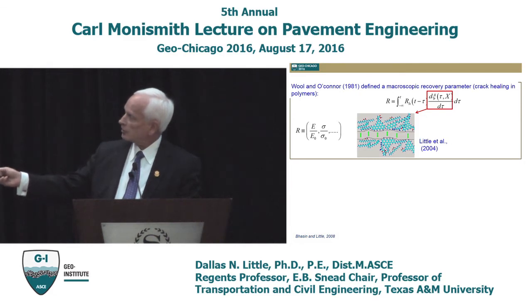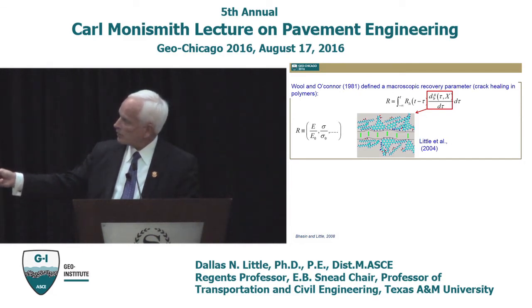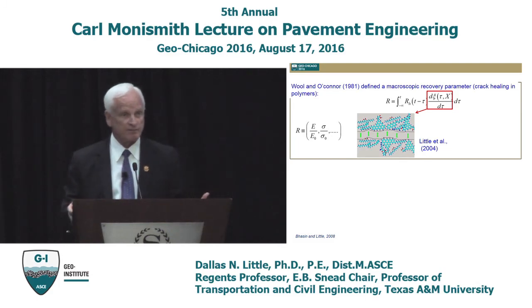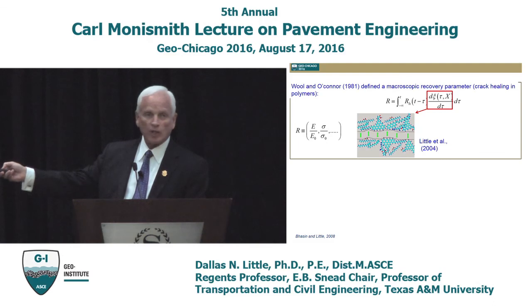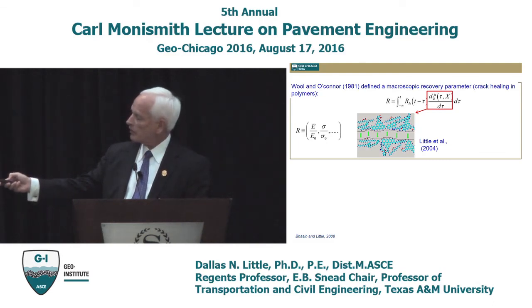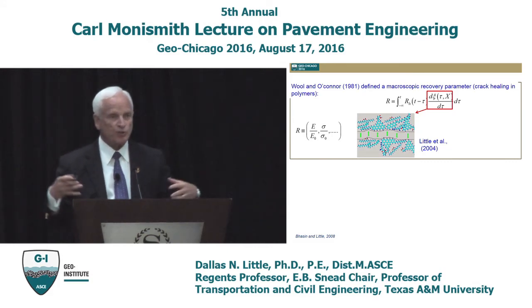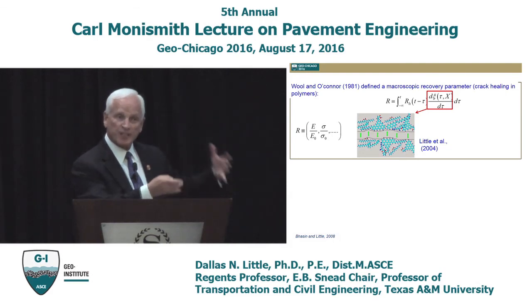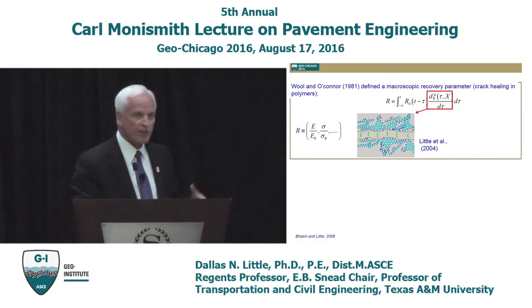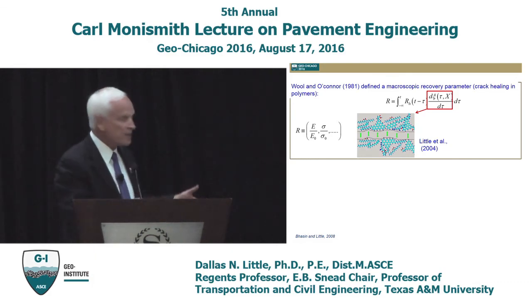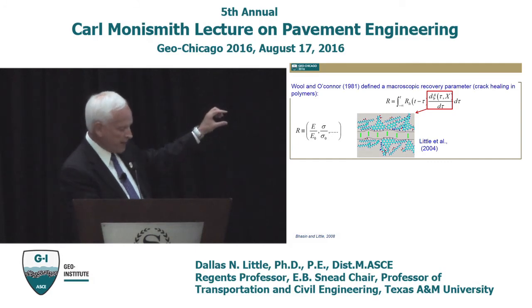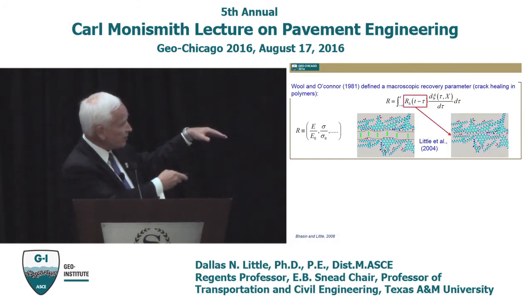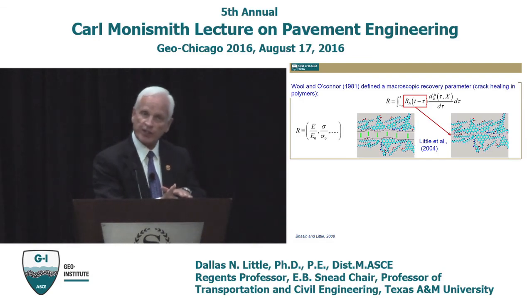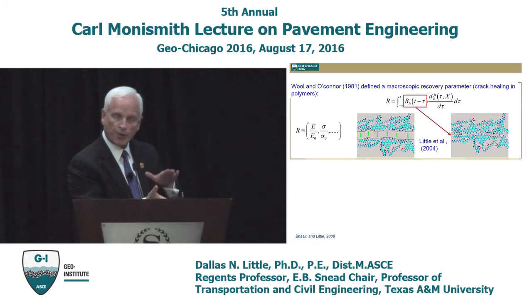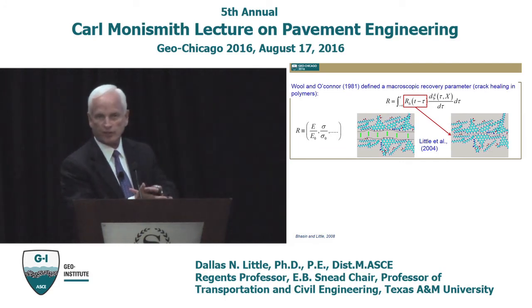And the first process is this term right here, which is related to the wetting of the cracked area. Now, my visual up here may be a little bit hard to see, but if you look on each side of a crack, this is an upper crack, that's a lower crack, I've got a bunch of molecules that are supposed to simulate the molecules that are typical in asphalt. If you could see it well enough, I think you would note that. Bottom, same thing. Well, when that crack is pushed back together, there's a wetting process that occurs. And that wetting process is directly related to the free energy of that cracked surface.